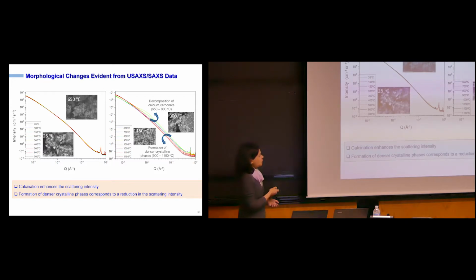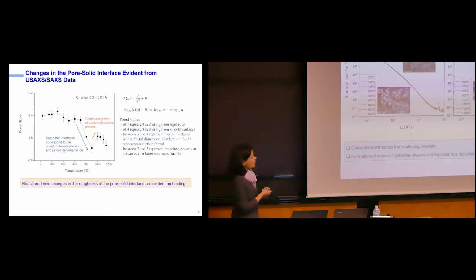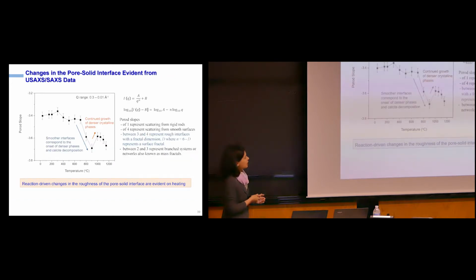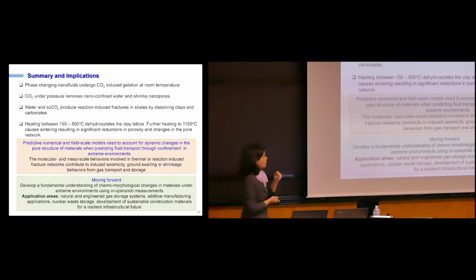Also looked at small angle scattering curves. Not a lot to report between the 25 to 650 range. A lot of interesting changes happening above that. Basically, what happens is as you start to heat, and you start to get some ordered crystals forming, you start to see some smoothing of these interfaces. At least that's what we infer from our scattering curves.